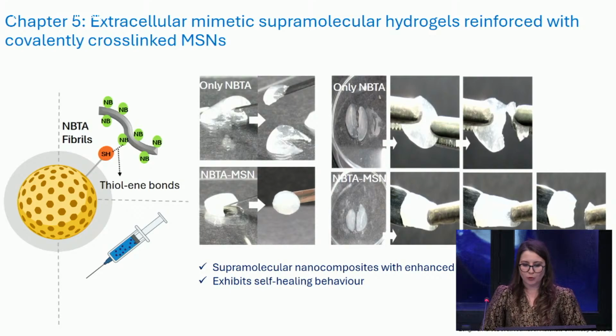In the system, norbornene groups on BTA fibrils were engineered to interact with the thiol groups of MSNs through photoinitiated thiol-ene interactions. And these interactions form a secondary network which significantly enhances the mechanical properties of BTA hydrogels. And interestingly, although we have a covalent network here, these hydrogels preserve their self-healing properties.